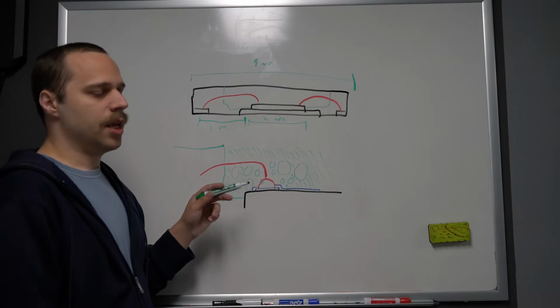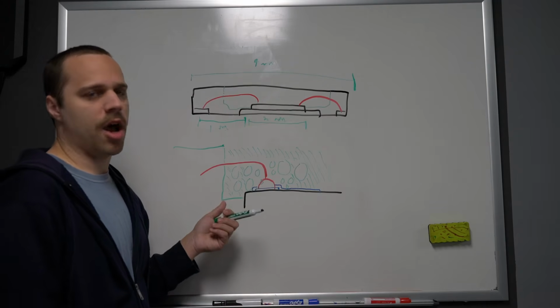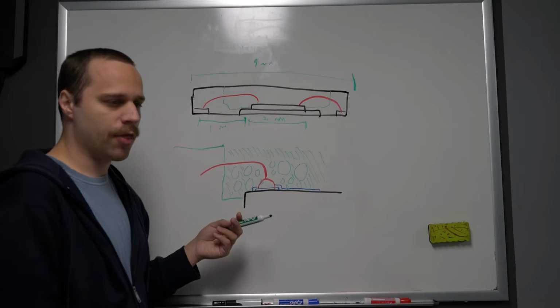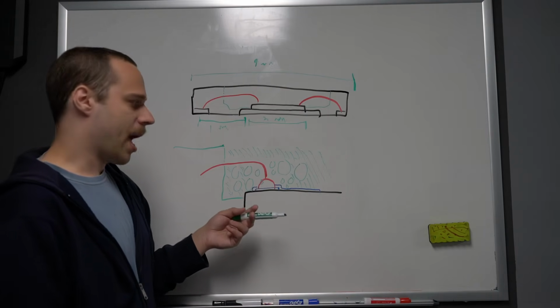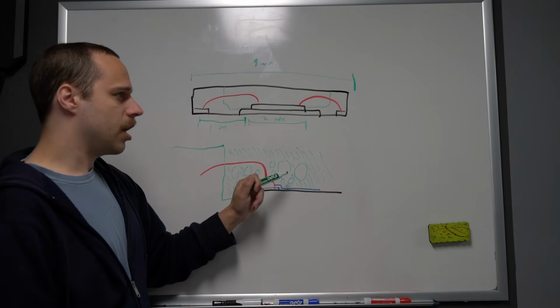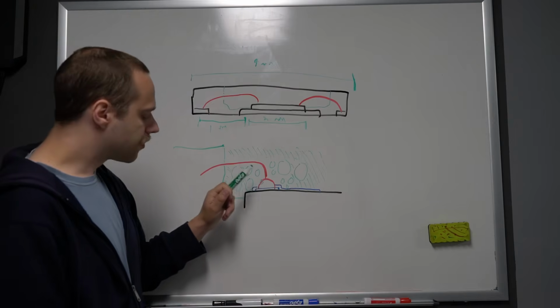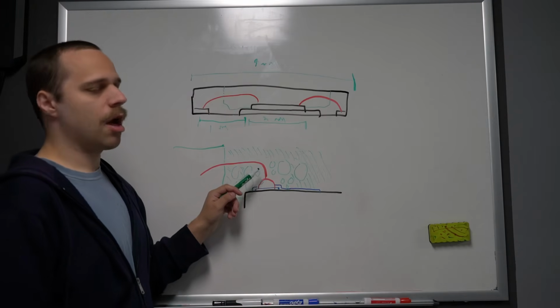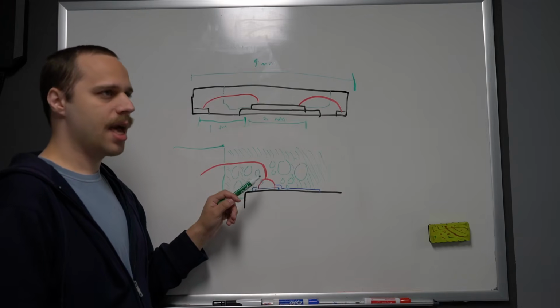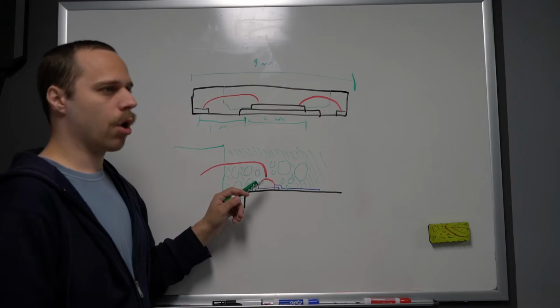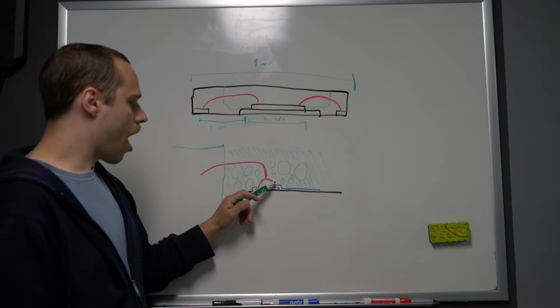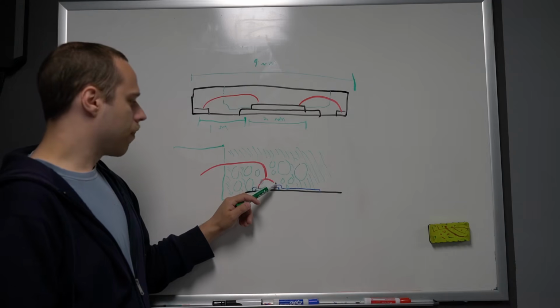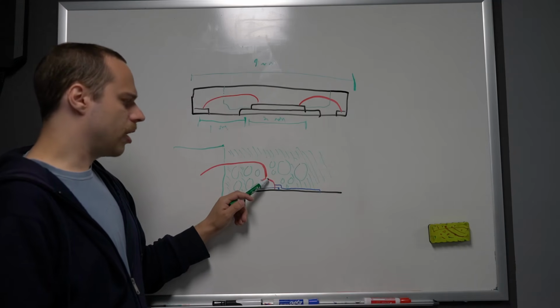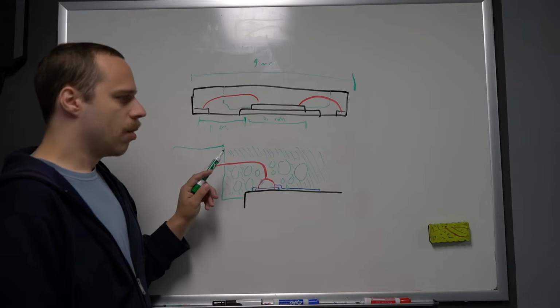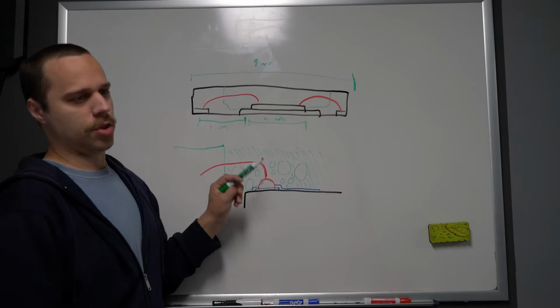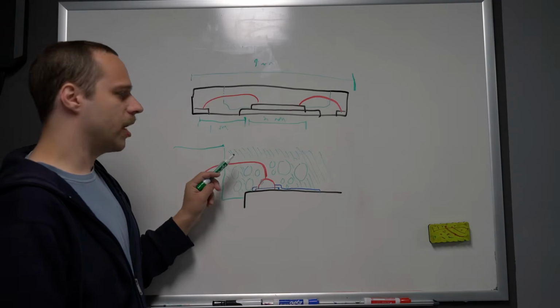Nitric acid is actually an interesting chemical because of its oxidizing and acidic nature, and depending on the concentration and presence of other things such as water, one or the other may dominate in any given reaction. And so we want to maximize the oxidizing nature, and we don't want it to be behaving like an acid more than necessary. Somewhat counterintuitively, as the concentration of the acid goes up, proportionally speaking, and the water concentration goes down, it will actually be more inclined to passivate metals. So specifically the copper, as the acid concentration goes up, you will form a copper, I believe, oxide and nitrate mix layer on the surface, which, if you don't have any water present at all, will not dissolve into the acid and will therefore provide a passivation that protects against further corrosion.